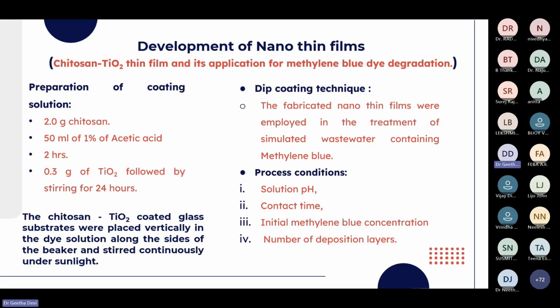nanomaterials on glass slides. We made the thin films by the dip coating method, that is, a glass slide is dipped into this coating solution. The fabricated nano thin films were employed in the treatment of simulated wastewater containing methylene blue. These coated glass substrates were placed vertically in the dye solution to be treated, along the sides of the beaker, stirred continuously, and exposed to sunlight. The processing conditions varied are solution pH, contact time, initial methylene blue concentration, and number of deposition layers.